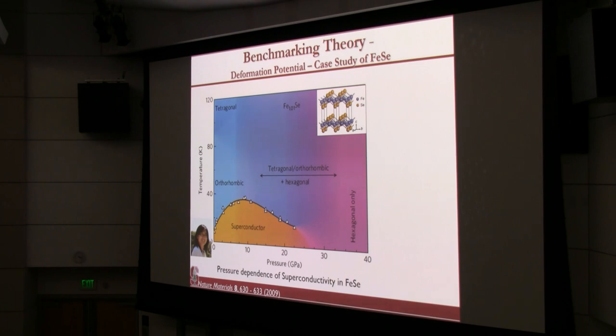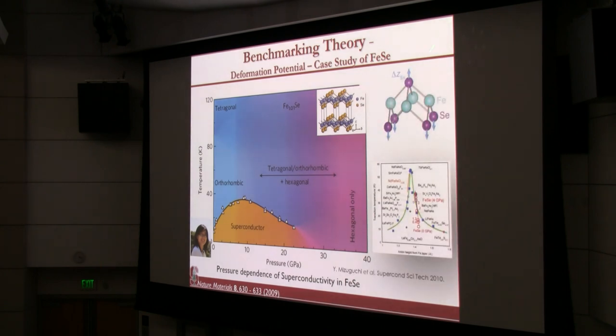It's a bulk, okay? Now, if you put a pressure in modern standard, it's fairly modest, okay? 8 Kelvin, 8 gigapascal, the TC go from 8 to close to 40. Okay, it's a very interesting change, okay? So what happens? It turns out that is the pressure dependence. It turns out what is important is the height of the selenium atom in the structure.